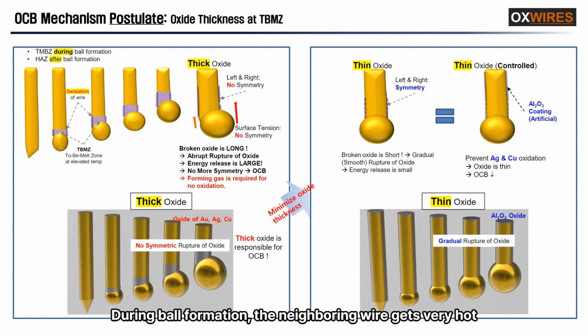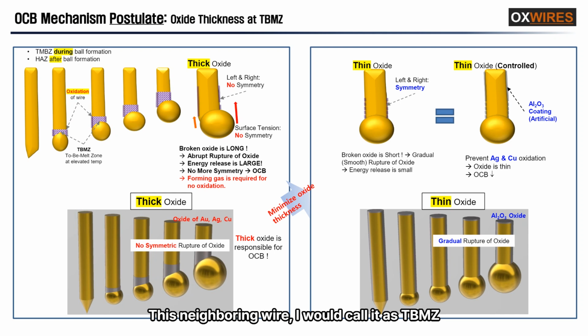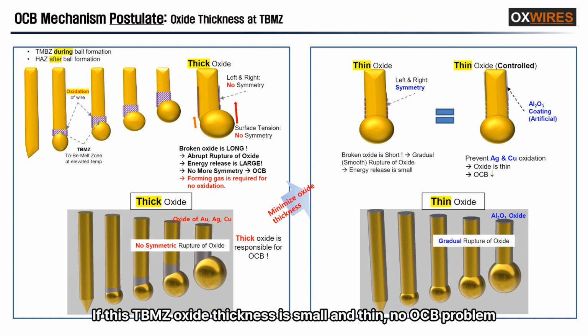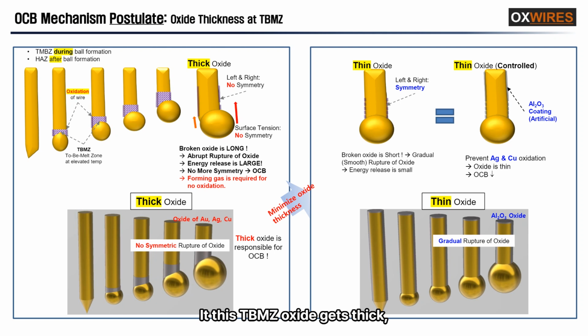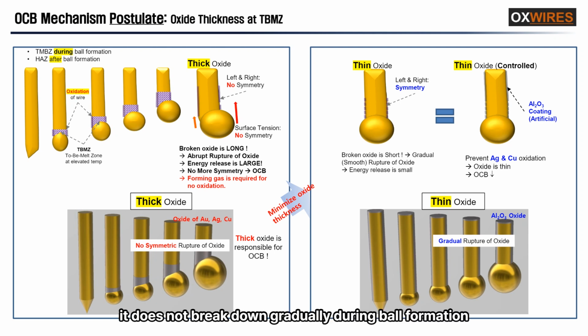During ball formation, the neighboring wire gets very hot. This neighboring wire, I would call it TBMZ. Even during a very short period of time, the surface of TBMZ experiences oxidation. This oxide thickness depends upon a wire material type. If this TBMZ oxide thickness is small and thin, no OCB problem. If this TBMZ oxide gets thick, it does not break down gradually during ball formation.